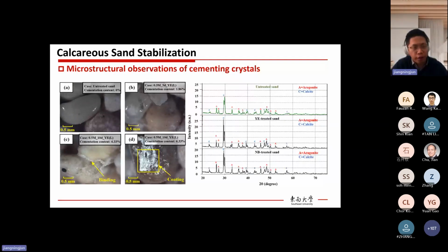Then after the cementation process, we used a microscope to see how cementation formed and how it was distributed within the soil structure. The first graph shows untreated sand, so we cannot see any cementation between soil particles. The second graph shows the slight cementation case, with only 1.86% cementation. We can see a little bit of cementation between particles, but not too much. The next case is a heavily cemented case, where the cementation content is more than 6%. Here we can see quite a lot of cementing agent between the soil particles.